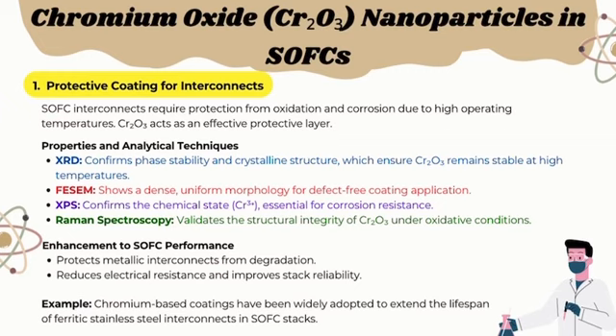Moving on to the properties and analytical techniques, when XRD is used, it confirms the phase stability and crystalline structure, which ensures chromium oxide remains stable at high temperatures. FESEM shows a dense, uniform morphology for defect-free coating application, and XPS confirms the chemical state of the chromium 3+ ion, essential for corrosion resistance. And last up is Raman spectroscopy, where it validates the structural integrity of chromium oxide under oxidative conditions.